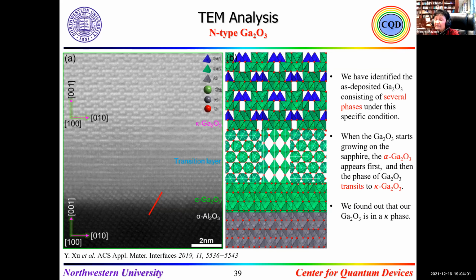But if you have the possibility, if you can do electron spin resonance, that is the best technique for this material, because you can have the fine structure, hyperfine structure, super hyperfine structure, you can find exactly the problem of the defect, the symmetry of the defect, the place of that, all of that. So really it's a starting point. So I hope that I gave you some answers.